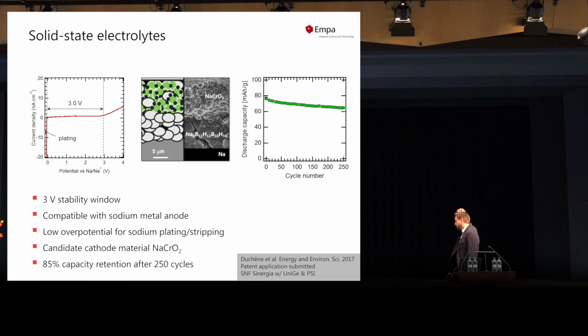So to build a full battery, we then joined the sodium metal anode shown here. We needed a separator, which is just our pure electrolyte. And then for the cathode side, we chose to use sodium chromium oxide as a cathode material. And in this cathode part, we have to basically mimic the porous structure of an electrode, which is typically infiltrated with a liquid electrolyte. But here we have to mix the solid electrolyte with the cathode material, and we were able, with this concept here, to stabilize a solid-state battery for 250 cycles with a capacity retention of 85%, which brings this type of material to the technology readiness level where other solid-state battery concepts are around.